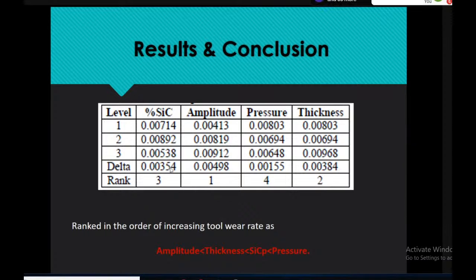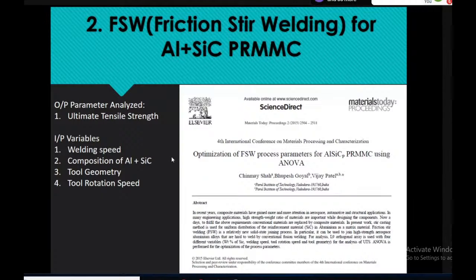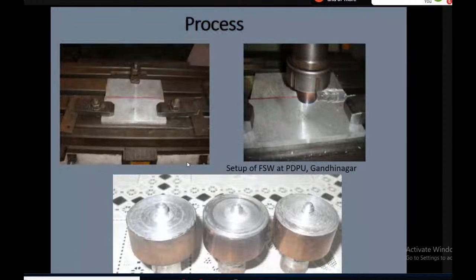Let us move to the second case study. With 2 of our faculty, Chinmay Shah and Vijay Patel, we worked on FSW, friction stir welding. In that we were trying to do optimization of FSW process parameters for aluminum silicon carbide particulate reinforced composite using ANOVA. We were trying to measure the ultimate tensile strength, which was our output variable. The input variables were welding speed, composition of aluminum and silicon carbide, tool geometry, and tool rotation speed. This is the setup available at PDPU Gandhinagar, and we performed our experiment there.